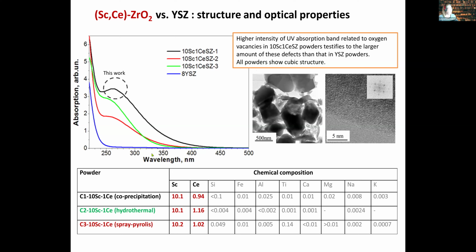And we take care of the optical properties. Exactly, we first check whether we have oxygen vacancies. I can tell you in advance that the amount of oxygen vacancies in yttrium doped zirconium oxide is quite low in comparison with scandium and cerium doped oxides. Most powders had nearly the same chemical composition. They differ in some impurities that we are not able to control. And all the powders had cubic structure, as was shown, for instance, in this TEM image for specific powders.